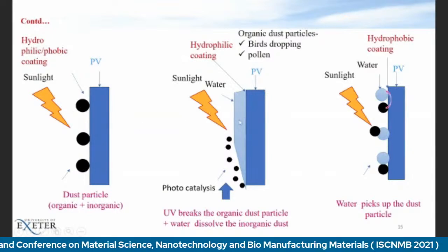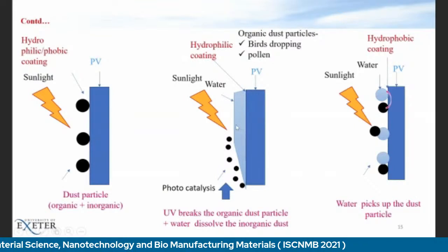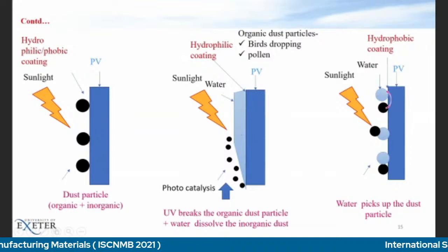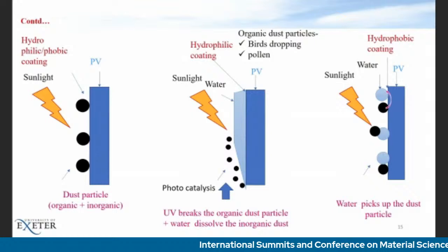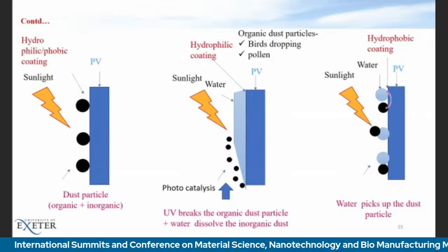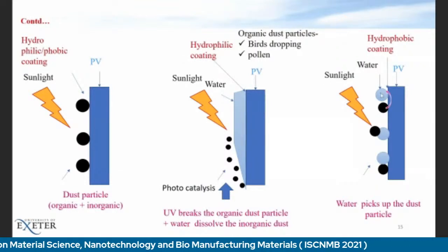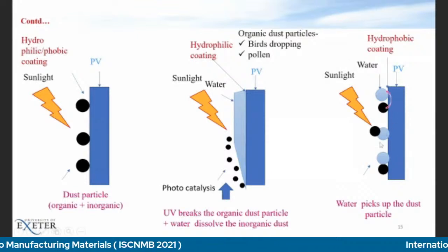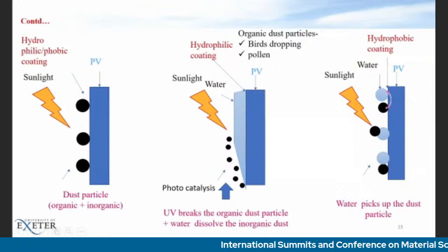So if your coating is a hydrophilic coating, the water actually just spreads there. Previously, most of the hydrophilic coatings were TiO2 based, and they are very much used with the photocatalysis process. It breaks the organic dust in the presence of UV when there is sunlight, and also dissolves the inorganic dust, so it can clean the surface. In case of the hydrophobic, it actually picks up the dust particles and then they drop from the surface. These are the two basic mechanisms using hydrophilic and hydrophobic coatings.